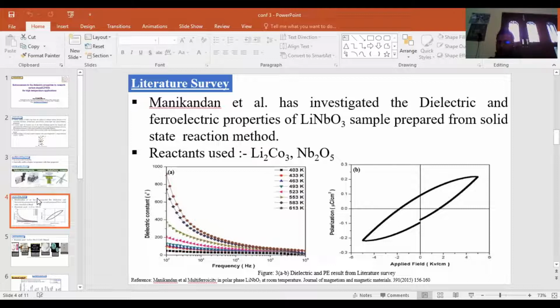In the literature, the dielectric and ferroelectric properties have been investigated by this team, and in figure 3a I have shown from the literature the dielectric constant characterization, which is up to 613 degrees Kelvin, and how it varies at different frequencies. And also in figure 3b I have shown the P-E characterization, in which the polarization value is almost 0.25 when the applied electrical field was 4.5 kilovolt per centimeter. I have also given the reference here.